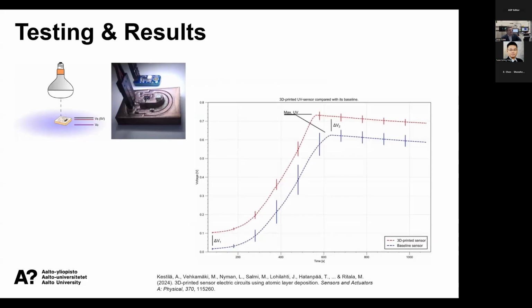And then we actually tested this. We had the normal one. We joined the components in the circuit, and then we put it to the test. If you look at the baseline sensor and this 3D printed sensor, it quite nicely follows the curve. Of course, there is some voltage difference, but it seems quite constant, so there is no huge difference there. That's actually quite good.